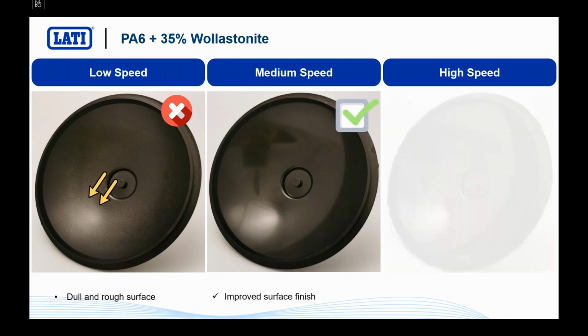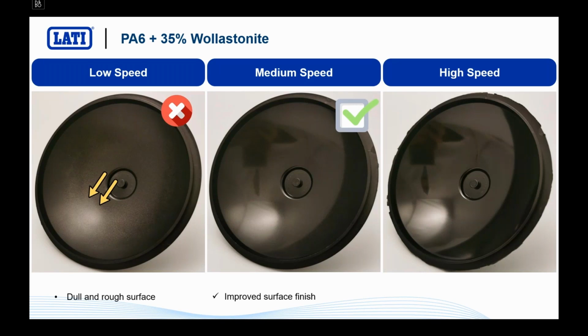But if you increase your speed too much, what happens is that you have flashes, because you have somehow increased too much the speed. The material became too liquid and it was squeezed between the two halves of the tool. Flashes are a main issue, not only from a surface finish point of view, but also from a technical point of view, because you have to deflash your part. Otherwise, it will be impossible to sell and to use it. And deflashing can take an overwhelming amount of time, and you want to stay away from flashes.